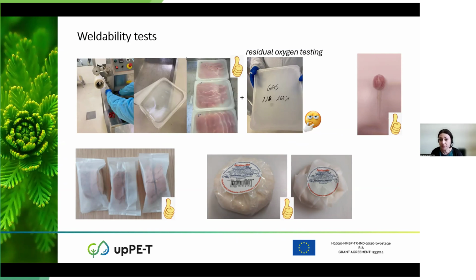So after some problems, some breaks, at the very end, it was demonstrated that at specific conditions, it was fine. Indeed, as you can see, this prototype is very, very nice. The flow pack mechanism was successful, so it works without specific problems along the trial from the mechanical and processing point of view. And also in the case of the Tomino, it worked properly. So it was possible to cut in proper way the flexible film and to pack properly. And also the label is fine and well adherent to the packaging.